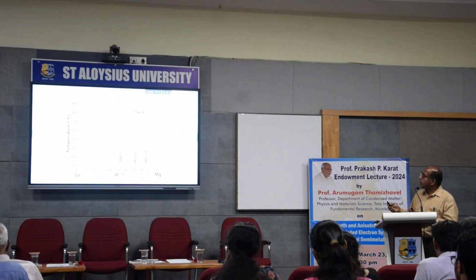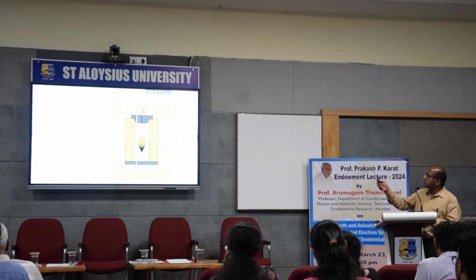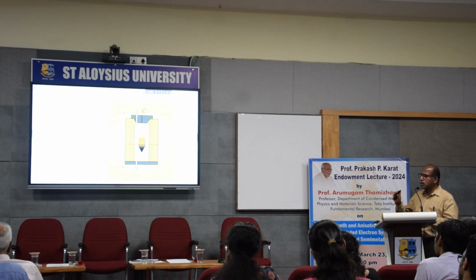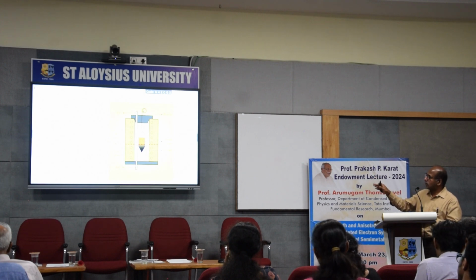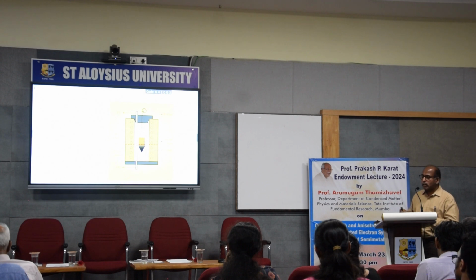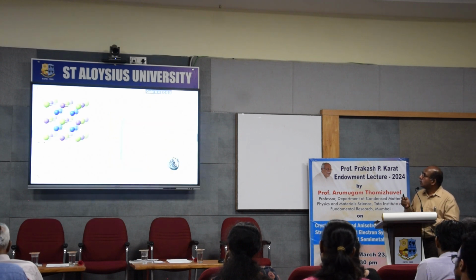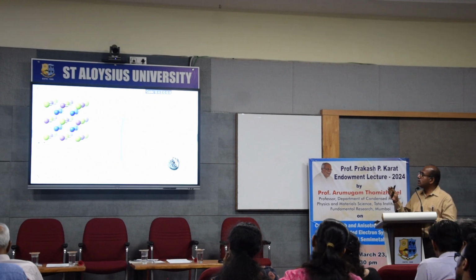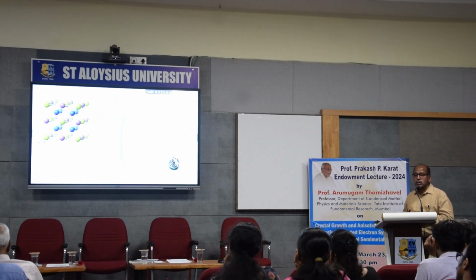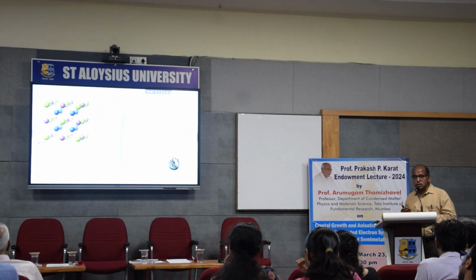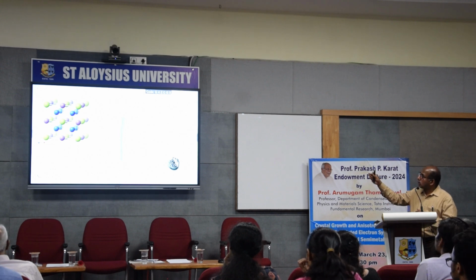So now I can employ Bridgman growth to grow this crystal. So this is the technique which I have used. I have this Bridgman furnace where I have taken the material in a sharp tip ampule and then applied a temperature profile, and I got single crystals. For that, it's not a very simple task. Magnesium reacts with quartz, so I have to seal it in a metallic crucible. So I have sealed it in a molybdenum crucible.